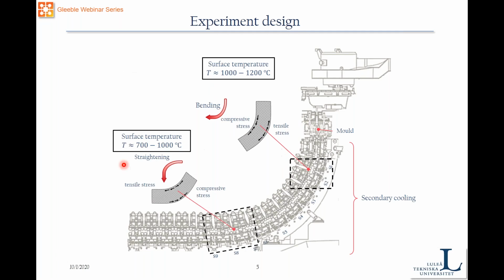The straightening, which is also considered a high-risk section or zone during continuous casting, is risky because the material here is almost completely solidified. So the temperatures here are going down, and again there is a combination of tensile and compressive stresses, knowing that tensile stresses are actually needed for creating cracks in the material.